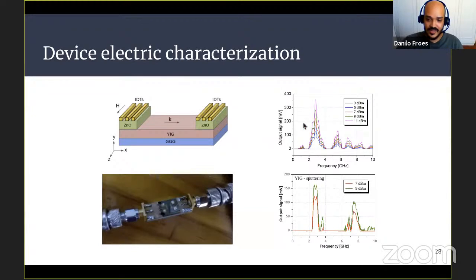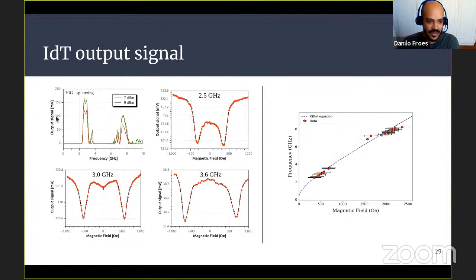So the liquid phase epitaxy sample was sent to Recife to do the Brillouin light scattering experiment, and the sputtered sample stayed with us here at CBPF. We repeated the experiment of exciting with the radio frequency and measuring the output signal while changing the magnetic field. Here's the spectrum, and by varying the magnetic field, these things happen.